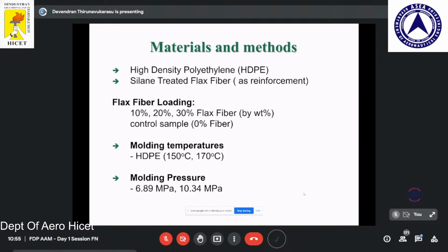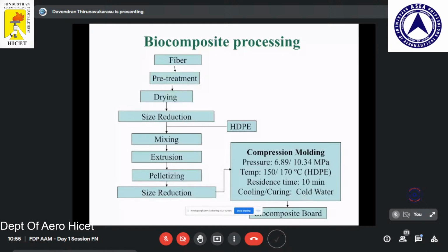So here we are loading 10, 20 and 30% of flax fiber, plus control samples, by weight. The molding temperature is 150 and 170 degrees Celsius, and the molding pressure we are varying between 6.89 and 10.3 megapascal. And this is the process.